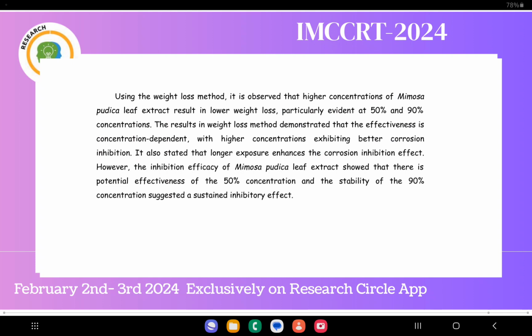Using the weight loss method, it is observed that higher concentrations of Mimosa pudica leaf extract result in lower weight loss, particularly evident at 50% and 90% concentrations. The results in weight loss method demonstrated that the effectiveness is concentration dependent, with higher concentrations exhibiting better corrosion inhibition. It also stated that longer exposure enhances the corrosion inhibition effect. However, the inhibition efficacy of Mimosa pudica leaf extract showed that there is potential effectiveness of the 50% concentration, and the stability of the 90% concentration suggested a sustained inhibitory effect.